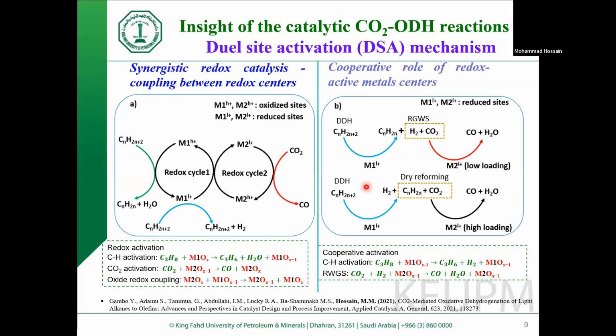In the next slide, we can see two metals, and this is the so-called synergic redox catalysis, a coupling between two redox centers. Here you can see metal 1 or metal oxide 1 interacts with the hydrocarbon to get the corresponding olefin, and then the reduced form of the metal can again interact with hydrocarbon to dehydrogenate the alkane to alkene. Now this reduced form of the metal can be reoxidized by a second metal, which is already oxidized. And this way, this metal will be going through the cyclic reduction and oxidation. The second metal will transfer oxygen to the first metal, and after reduction, it will interact with CO2 to reoxidize it again. So this way, there is a synergy that can be established to continue the process.